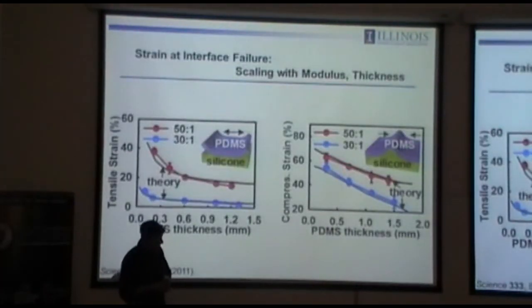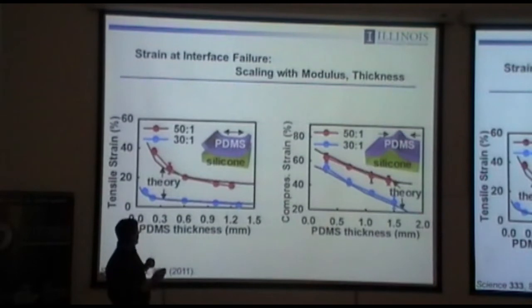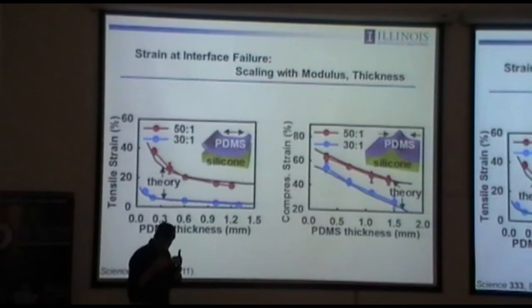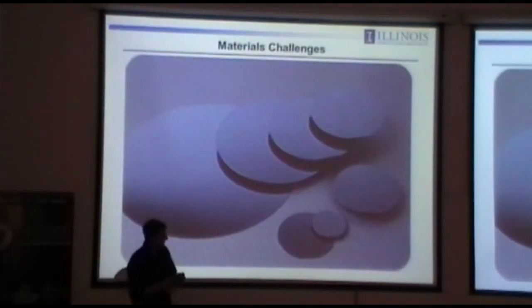And you can do that at a quantitative level. You can do experiments not involving skin, but using kind of artificial skin and the silicone, and then PDMS with different mixing ratios causing different stiffnesses. At different thicknesses, you can look at the compressive strain at which delamination initiates. You can do theory and you can do experiment. And so we know everything about the interface and mechanics associated with these systems. So we understand the impact of modulus and thickness on this critical property associated with skin-mounted electronics. So then the question is, how do you get there?